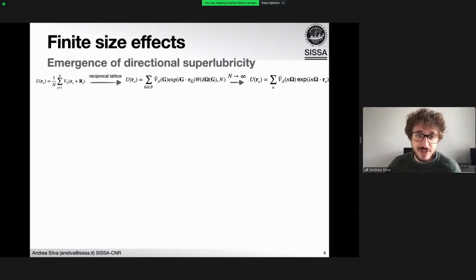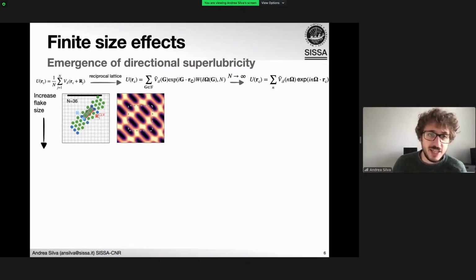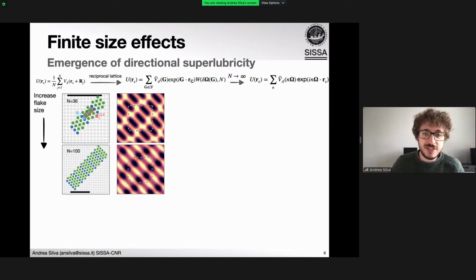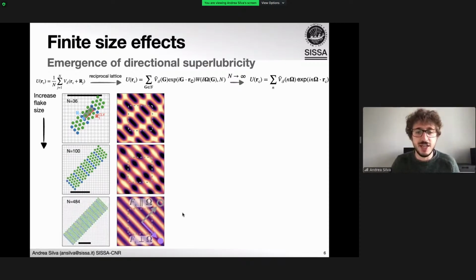We can play the same game with the new directional superlubricity we discovered. By increasing the size, we go from a clearly directional lock, with jumping between the minima of the potential, which are the black spots, to developing friction anisotropy, and in the end we have this true ridge and valley energy landscape.